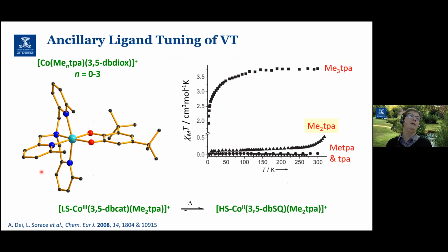Another really nice family of complexes from the literature was published by the Florence group of Andrea Dei and Lorenzo Sorace and their collaborators back in 2008. In this family of complexes, we have a cobalt and now one 3,5-ditertbutyl dioxolene and a tetradentate nitrogen donor ancillary ligand. These ancillary ligands are based on tripicolyl amine. You can functionalize them by sequentially putting methyl groups in the 6th position very easily, so you can actually access a family of 4 ligands: the one with no methyls, 1 methyl, 2 methyl, and 3 methyl.